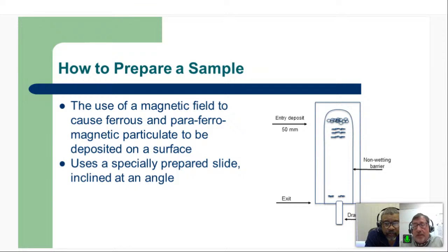What's really nice about this is that the magnetic field allows us to see the size distribution of the particulate by catching and concentrating the larger magnetically susceptible particles at the beginning where the oil is first introduced, and then smaller particles as we move further away. It also has the effect of orienting the particles in these magnetic lines of force that run perpendicular to the flow. And so you see them get lined up if they are ferromagnetic. If they're not, they're randomly oriented, as well as making their way further down the slide before they actually get stuck to the surface. So very quickly, we can look at that arrangement and distinguish between ferrous and non-ferrous particles, see the size distribution of the ferrous particles, and so on.